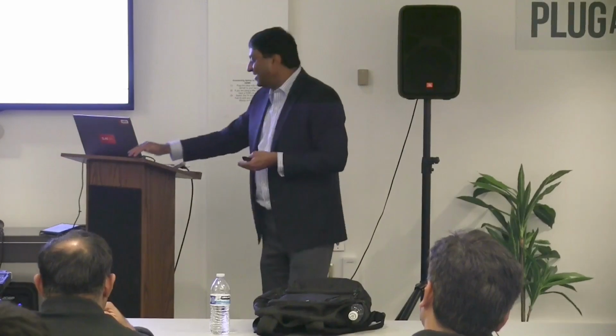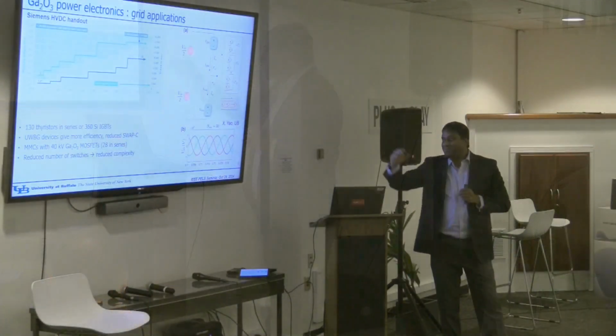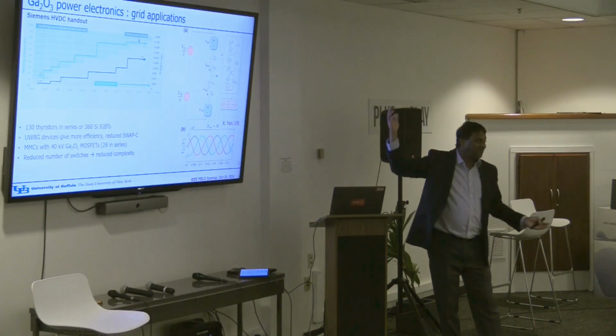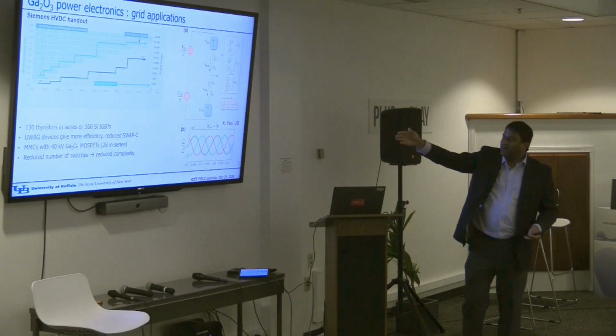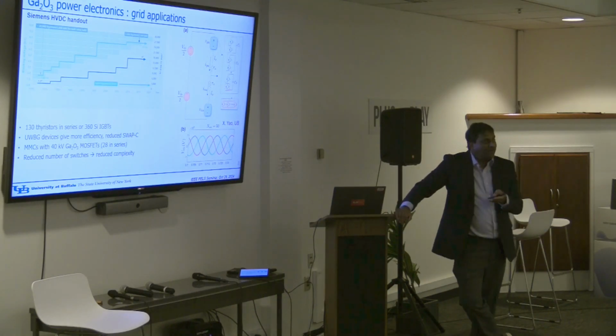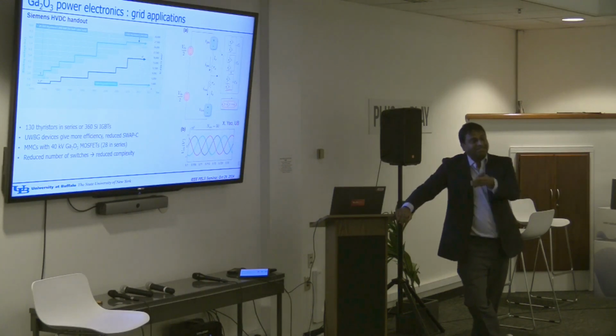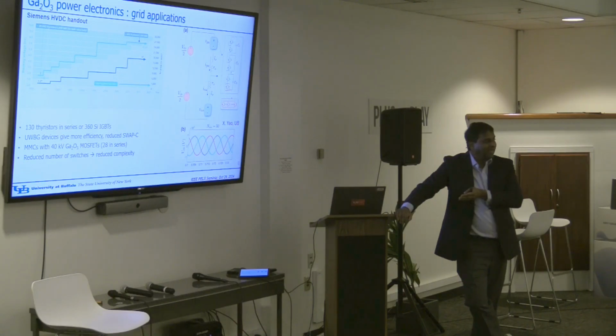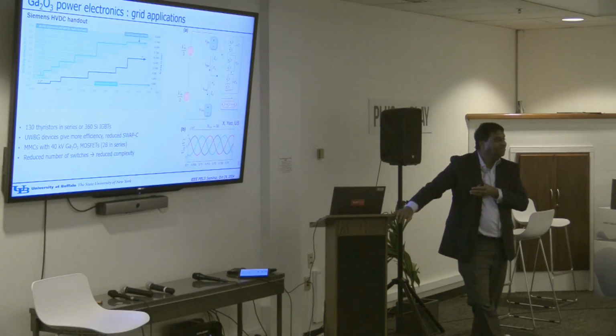Again, if you're using Baliga's figure of merit with a triangular field, using 8 megavolt per centimeter as the peak field, if you want 40 kilovolt, you need about a 100 micron drift layer, right? If you are a growth person, you would know that's reasonable. You can grow a 100 micron drift layer. It's still very hard to grow 100 micron thick drift layers, and you have to grow very high quality material, right? But if you want to do it with silicon carbide or gallium nitride, it would be 500 micron, or 800 micron, right? So clearly, with ultra widebandgap semiconductors with high field strength, you could imagine 20 to 40 kilovolt switches, and that would definitely reduce the number of switches and reduce the complexity, right?